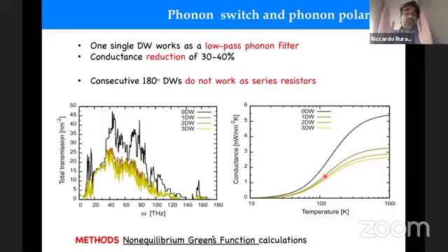And so when you are doing your filtering effect with the first domain wall, and when you hit the second domain wall, almost nothing happens. Okay, so this is by construction of this computational technique, which is fully harmonic. In molecular dynamics, this happens only when they are close, because the phonons don't have enough time to randomize again and to recreate the equilibrium population. But you do observe it when they are very, very separated. Okay, so you have these complementary views on the same physics.